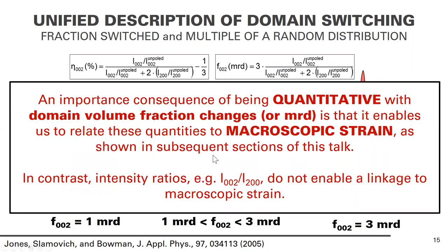All right, so an important consequence, this is not an arbitrary equation. An important consequence of this equation and the fact that it's quantitative with domain volume fractions or MRDs is that it enables us to relate these quantities to macroscopic strain, as we'll show in the subsequent sections of this talk. And I'd like to emphasize that in contrast, simple intensity ratios like taking the 002 over 200 do not enable this linkage to macroscopic strain. And so that's one of the values of these types of descriptors.